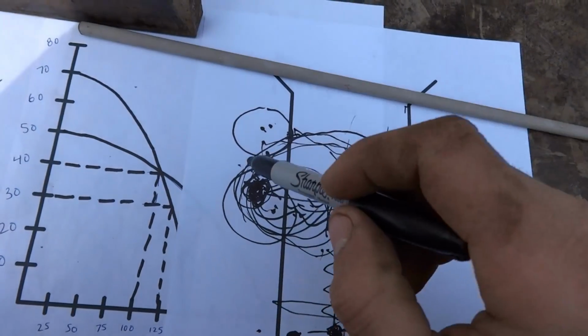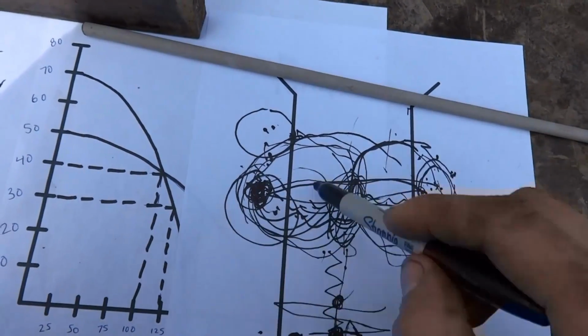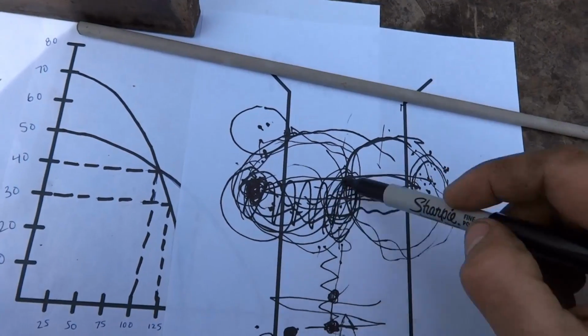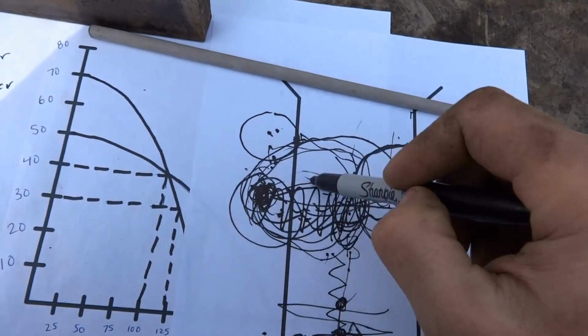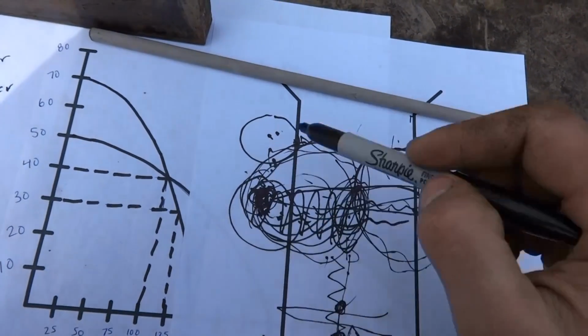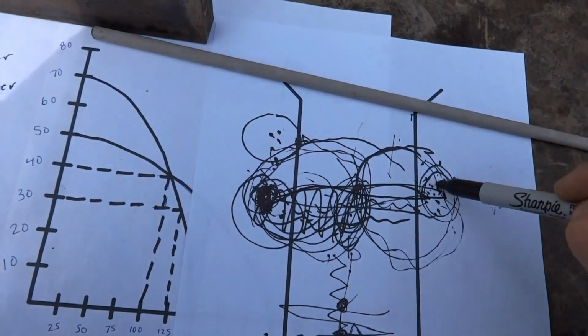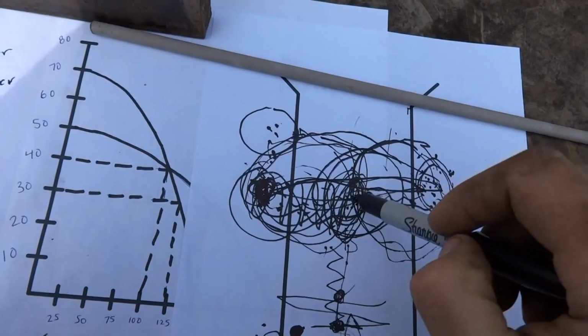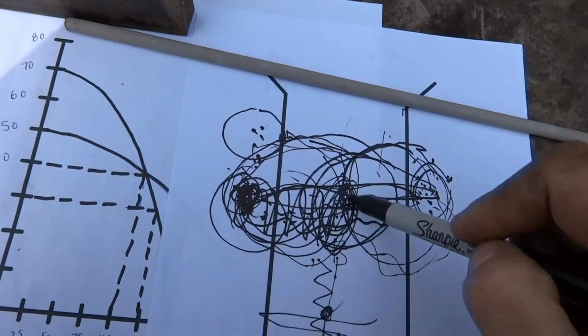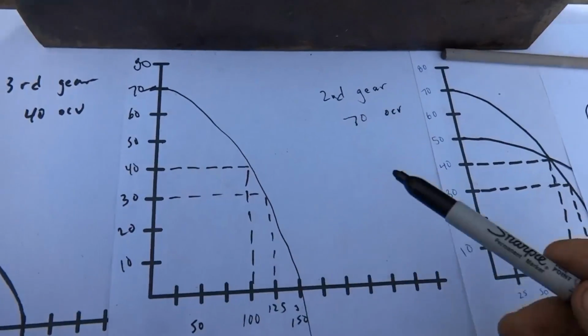However, if you want to burn through, then you put it to low amperage and high voltage setting, and when you move from here to over here, your puddle is still going to be liquid, and you're trying to stack metal on top of metal that hasn't solidified yet. The heat's going to travel and collect up in the middle here. You're going to blow a big hole, and it's because you don't know how to set your machine.